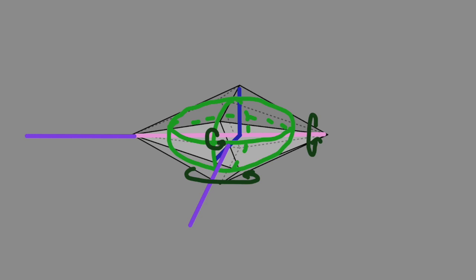And so double refraction will happen in a birefringent crystal as long as our light beam is not traveling directly along this axis. Since there is one such axis, the other two being the same, we call this a uniaxial crystal, and this axis is called the optic axis.